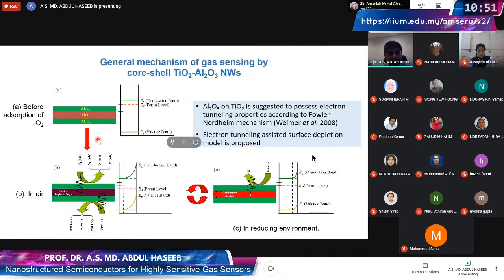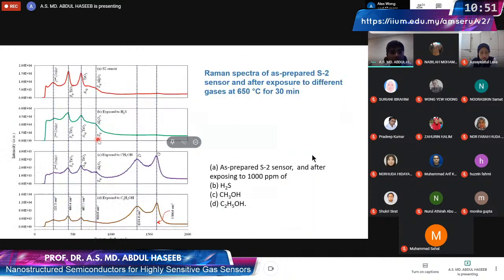So it is not behaving as an insulator. Otherwise, we would not get any signal. It is behaving in a way that it allows tunneling, electron tunneling, and then gives us the signal that we need. And after we have done this analysis of gas sensing, we also need to look at what happens to